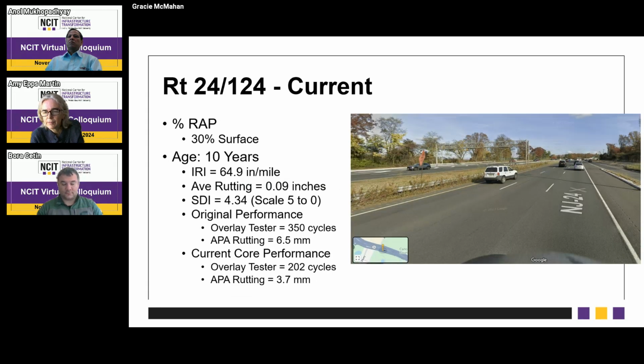Next slide, please. Going to the next youngest of those 5 sections, this is one after 10 years with a higher RAP content at the surface. Again, the original cracking performance was 350 cycles, and it's down now to 202 cycles, but that's still very good after 10 years. The rutting is still very low. The surface distress index is also still very high, 4.34. Also, you see the International Roughness Index. That's an indication of ride quality, is also being monitored. And anything less than 95 is still in very good condition.